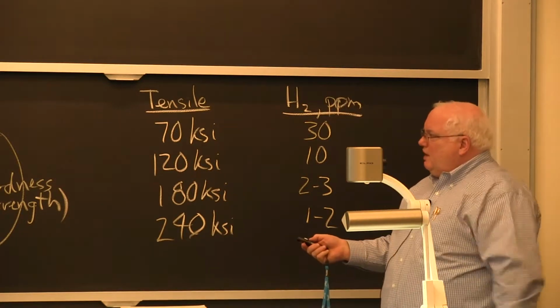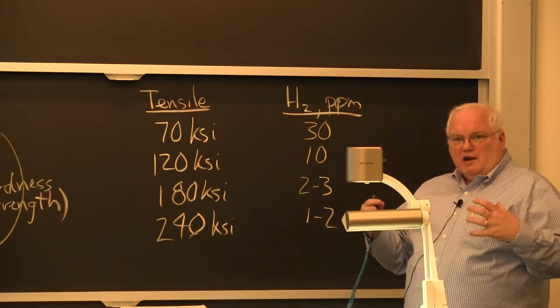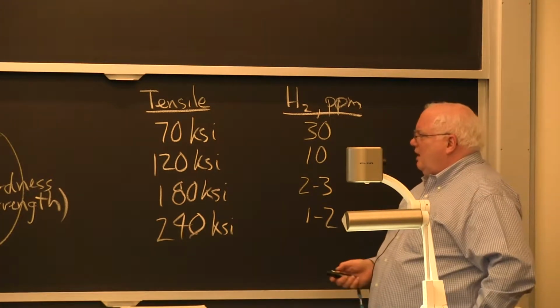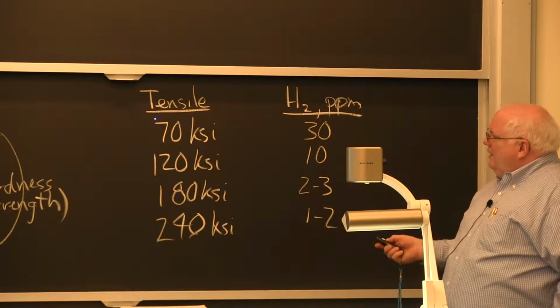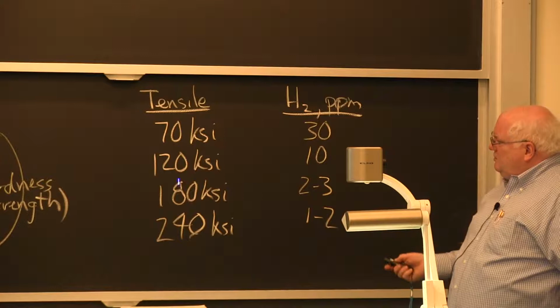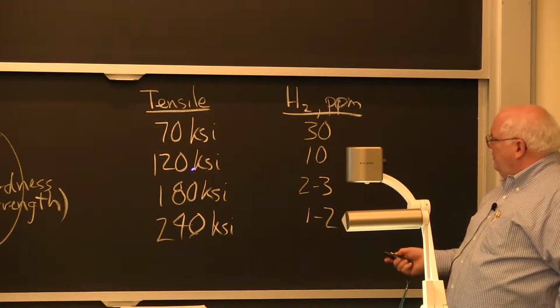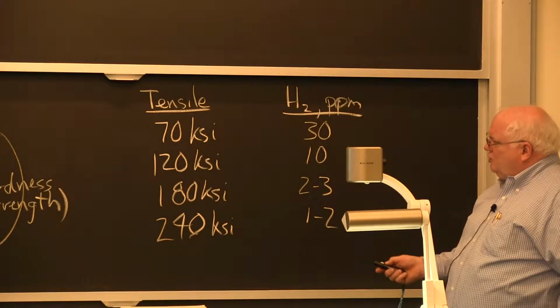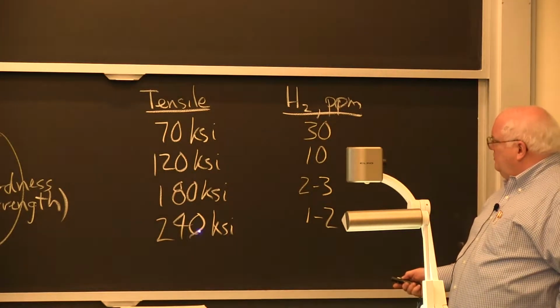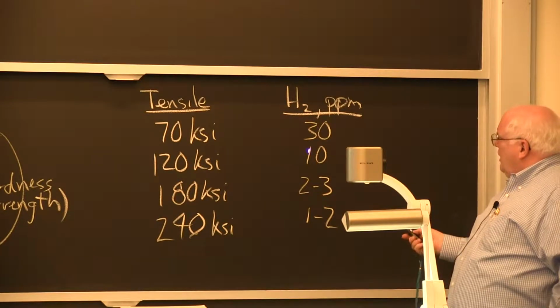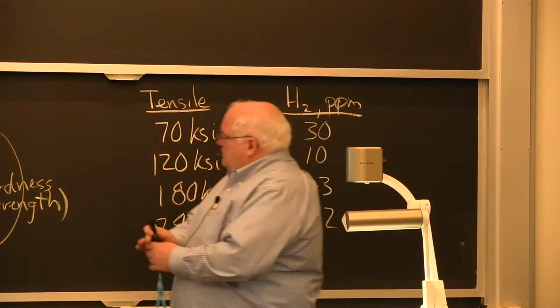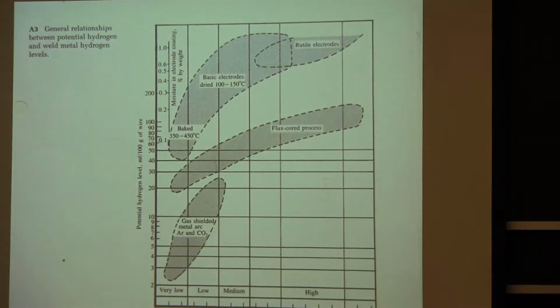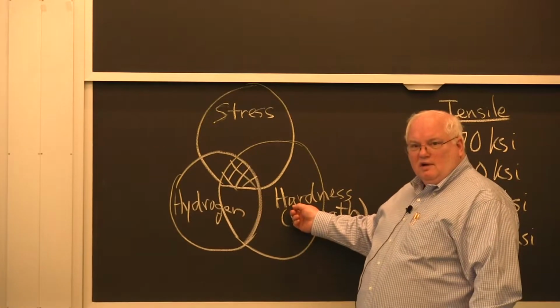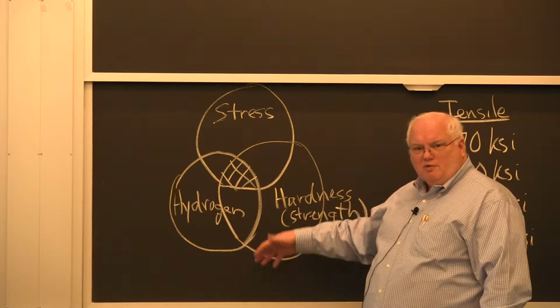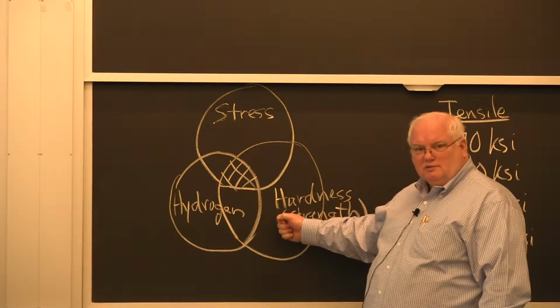The yield level residual stresses are the highest stresses you're going to get. In some cases, in something like that, you can actually get higher than yield because you get triaxial stresses, but we won't get into that, okay? But your stress can get as high in thick sections as whatever the tensile strength of the material is. So since your stress circle can get bigger and bigger as you go up in strength, you can tolerate less and less hydrogen, because as this circle gets bigger, this one better get smaller in order to avoid that, right? Or you need to control your hardness. It means you start with a steel with a low carbon, because remember, hardness is proportional to carbon, right?